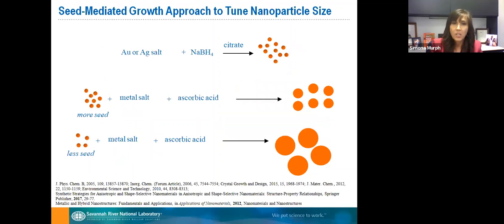Here, a typical procedure: you take a gold or silver salt, you use a reducing agent, and you also add a surfactant that will allow you to keep the nanomaterials together, and you create, for example, seed nanoparticles. Of course, if you want to grow the size of these nanoparticles, you can use this first step of the small nanoparticles, and you can grow them into larger particles by adding more metal salt and some reducing agent. And you can continue this reaction and increase the size of these nanoparticles.